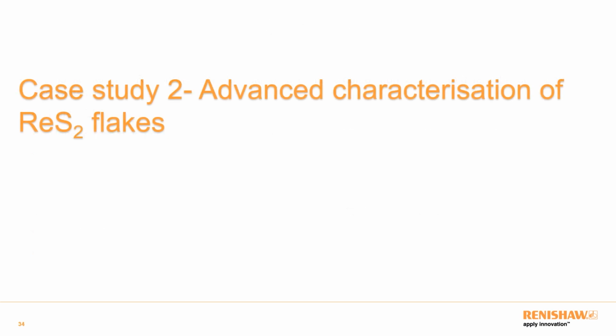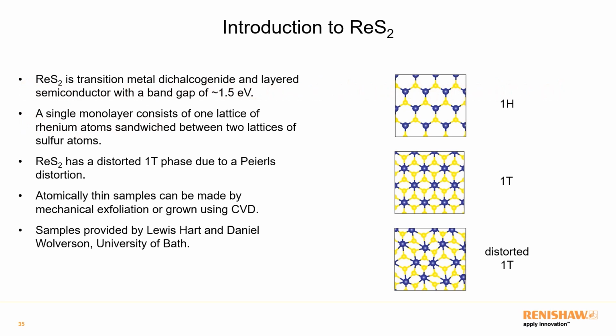Now I'd like to go on to my next case study, advanced characterization of rhenium disulfide flakes. Rhenium disulfide is a transition metal dichalcogenide. It's a layered semiconductor, hence a 2D material. It has a band gap of about 1.5 eV. One of the really interesting things about rhenium disulfide is it has a distorted 1T phase, and this is due to a Peierls distortion. And this means that it has quite interesting crystal properties. It's very anisotropic, and that makes it very interesting for Raman spectroscopy because it has lots of different Raman modes.